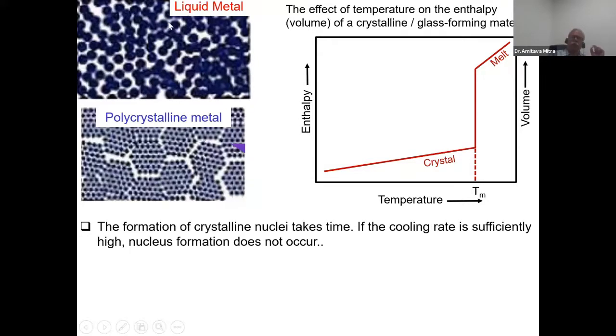So when you go from the liquid state through this process, the material will be formed in a crystalline phase, as a polycrystalline material with grains in between. The formation of crystalline nuclei takes time. If the cooling rate is sufficiently high, nucleation formation does not occur. This equilibrium process is a slow process.